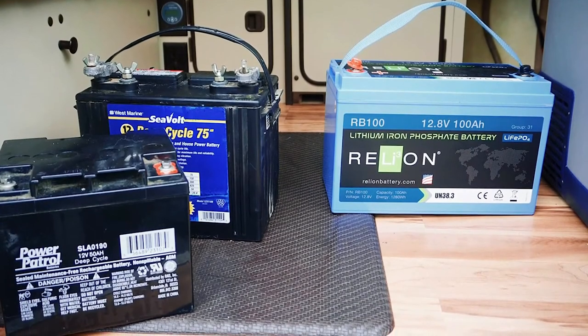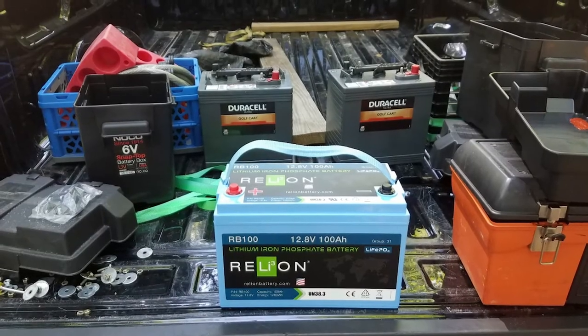Overwatering a lead-acid battery, which is usually caused by watering the battery in a discharged state, causes the electrolyte to overflow out of the vent caps. This results in a loss of sulfuric acid from the electrolyte in the battery, which can never be replaced, as only water should be added to the batteries. The loss of electrolyte will forever alter the chemistry of the battery, as the specific gravity of the electrolyte will never be restored to its design criteria, again resulting in reduced capacity and life.